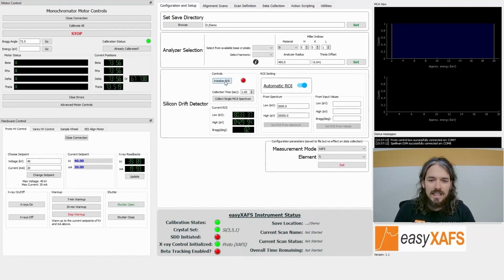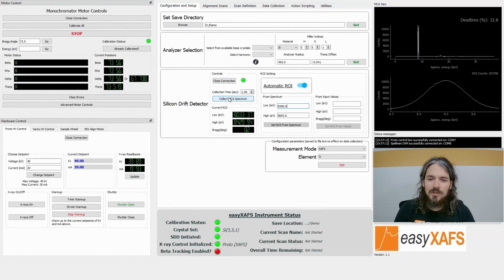Next we can initialize the connection to the detector. Since I already have the shutter open and the beam is on the detector, I can hit Collect MCA Spectrum, and the detector acquires a 1-second spectrum. You can see this spectrum at the top right. Since we're using an SDD detector, we're measuring the number of X-rays and the energy of each X-ray acquired. So we have an energy spectrum of all of the X-rays measured. The energy scale goes from 0 to 40 keV. For the silicon 551 analyzer, there's a single intense peak from the monochromatic beam at around 8.5 keV. These are the X-rays that we're interested in. That's what we want to use for our measurement.